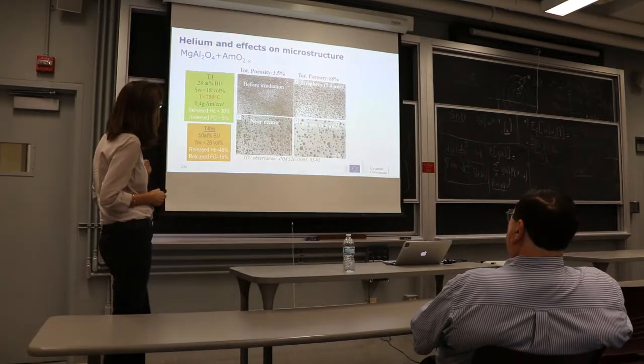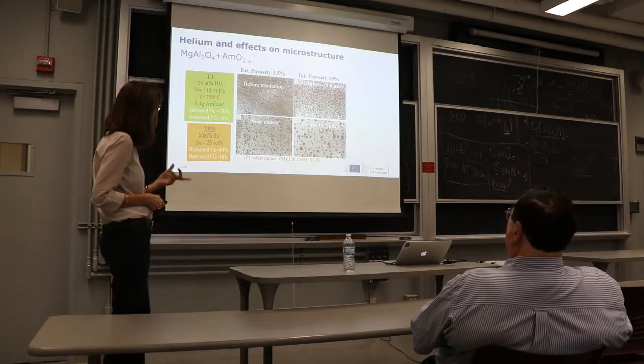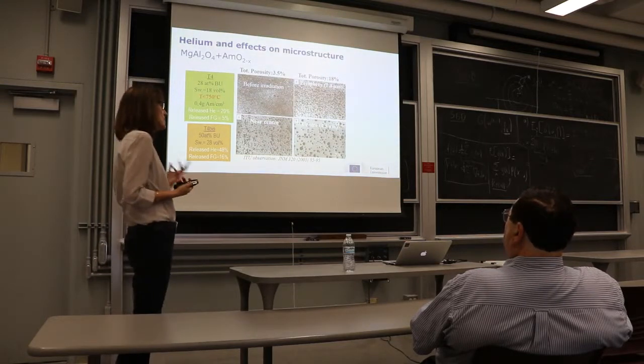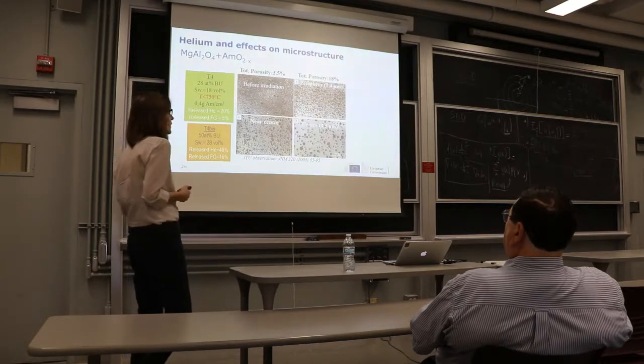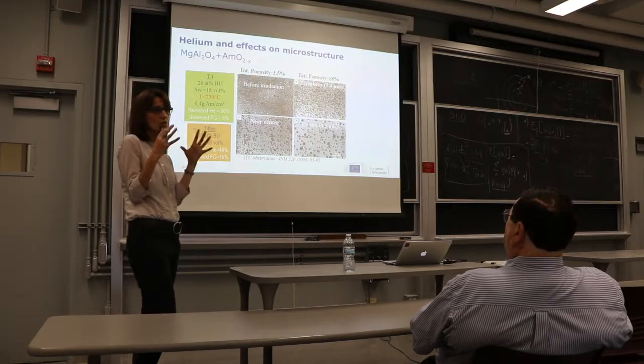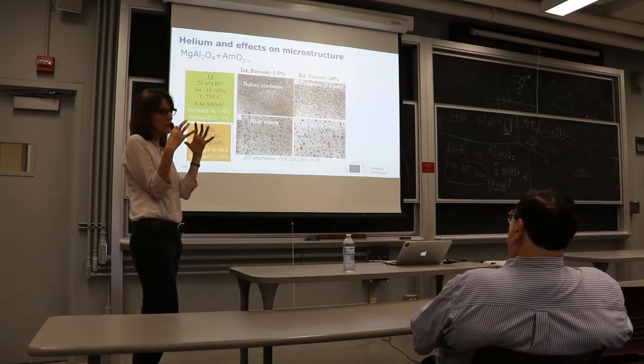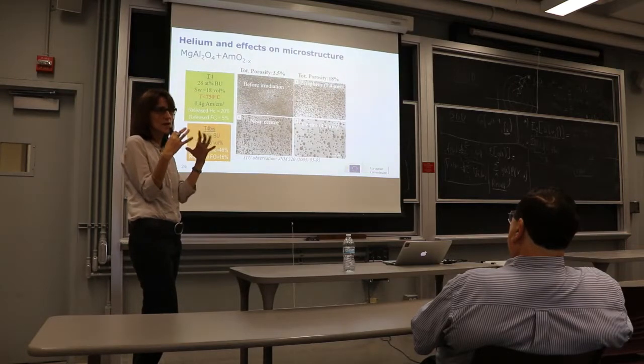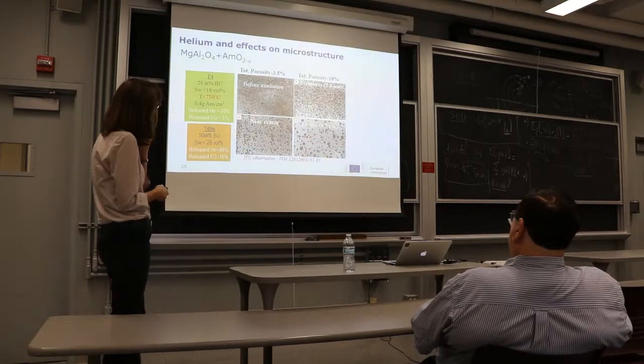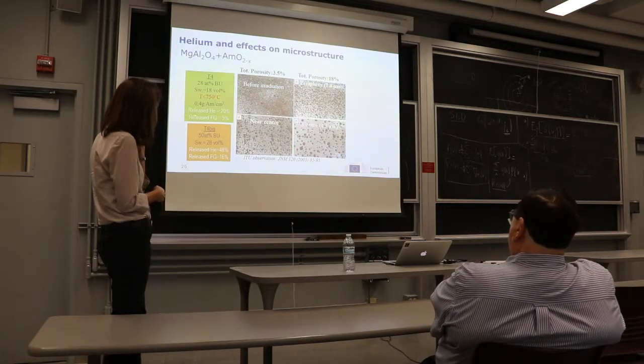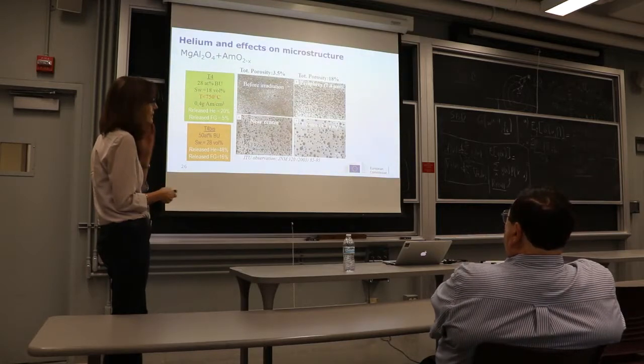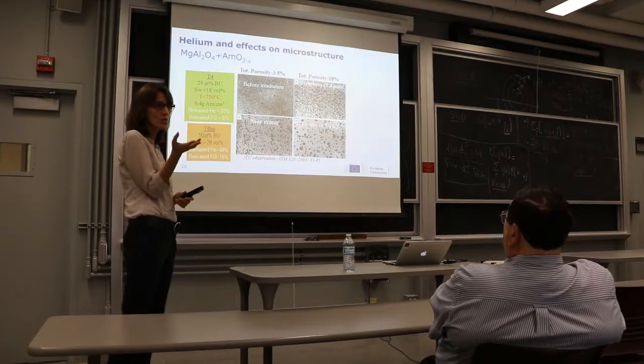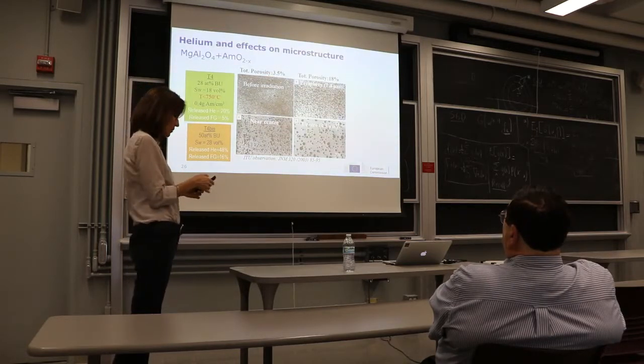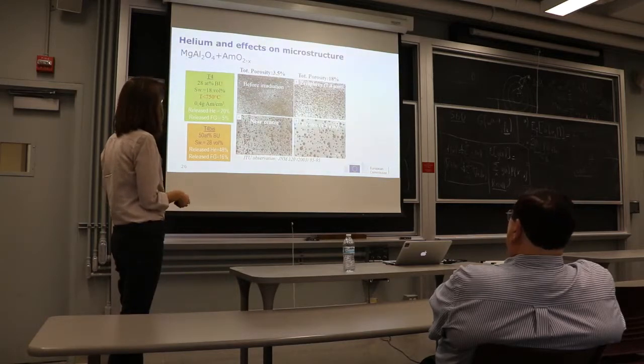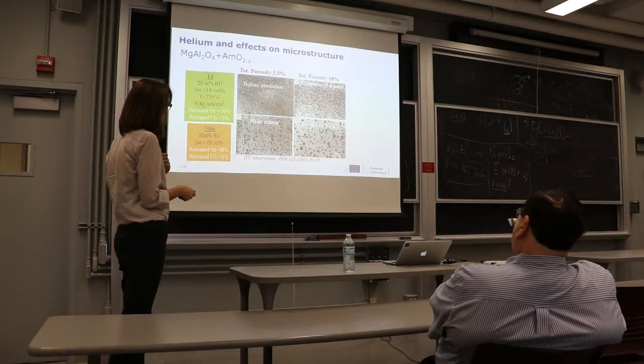And after irradiation, you see that the porosity increases quite a lot and also changes depending on the position where one looks. And this increase of porosity has as a consequence the increase of the dimension, which we call swelling. So it starts to increase in dimension, and you can imagine that this is something unwished inside a reactor. After doing all the analysis, it was clear that the swelling is due to the fact that while irradiated, the americium produces helium, and the helium is trapped partially inside these pores, and partially inside the matrix.